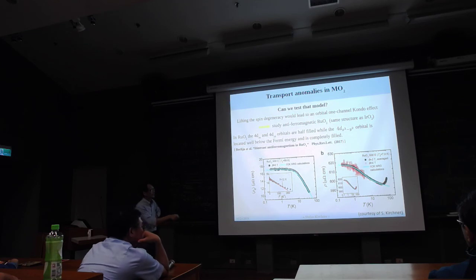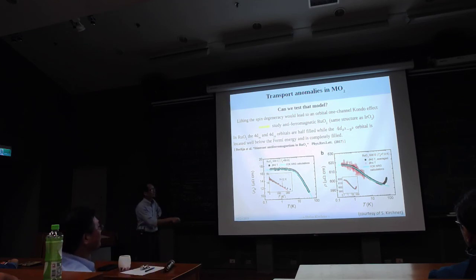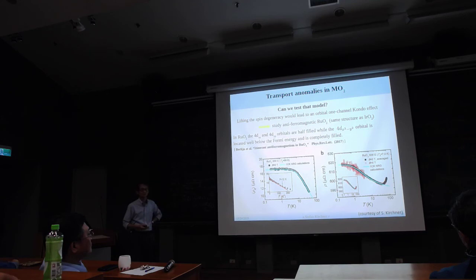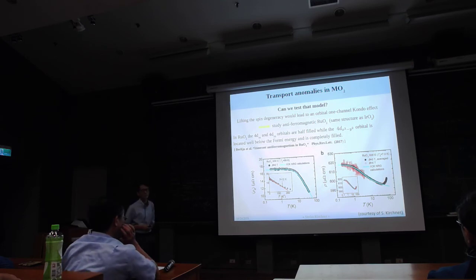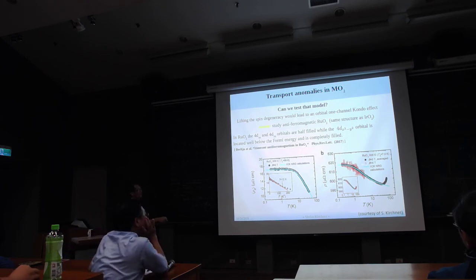In this case, black symbols are zero field, red symbols are in magnetic field. You see again that there's no magnetic field dependence. There are some fluctuations, that's a different story. But we observe a Kondo effect that obeys a universal 1CK functional form, with no magnetic field dependence.